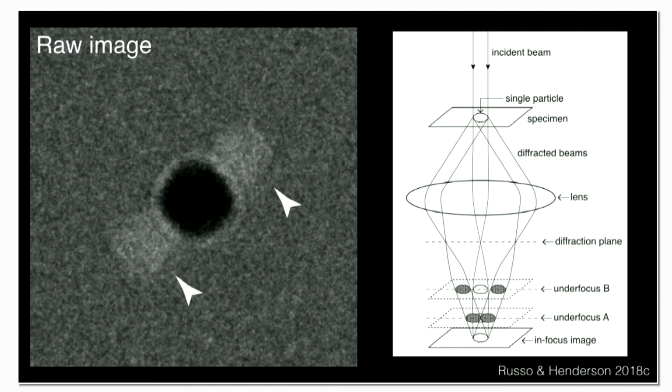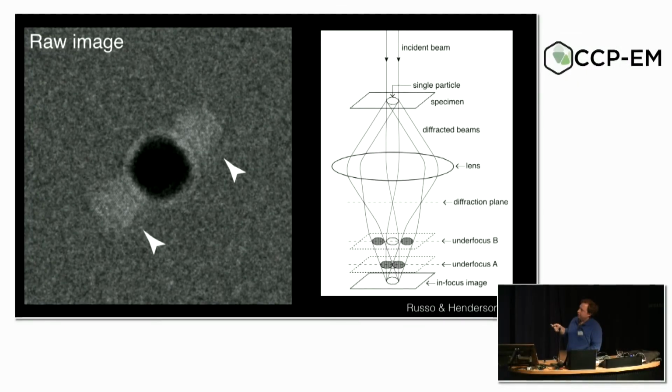And that you can see here. So this is just a raw micrograph of one of these gold particles in ice, low dose, just as we would image. And here are the 2 angstrom lattice reflections. So you can imagine if this were a ribosome or a virus, then all of the high resolution stuff that you're really after is actually out here at this particular defocus.